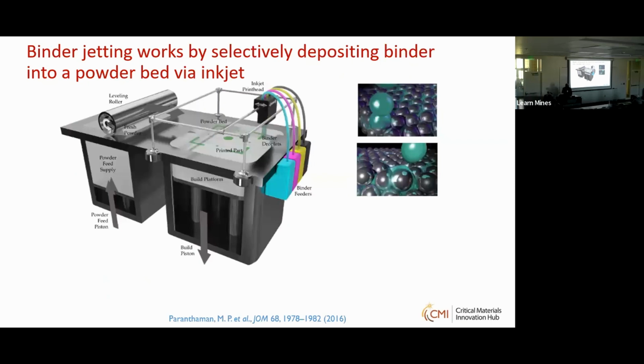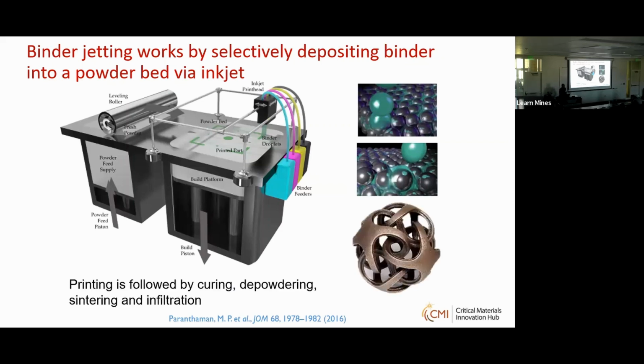And the other thing, some of you may be familiar with binder jet. The binder jet is more like an inkjet process. You have a powder bed and you are building layer by layer. Here you are not limited to spherical particles, so you can use non-spherical needles. A lot of times anisotropic magnets are needle shaped, with different particle shapes. You can use those and use a resin layer by layer, heat treat, and do all this process. Once you do the printing, curing, and depowdering, you can make complex shapes.